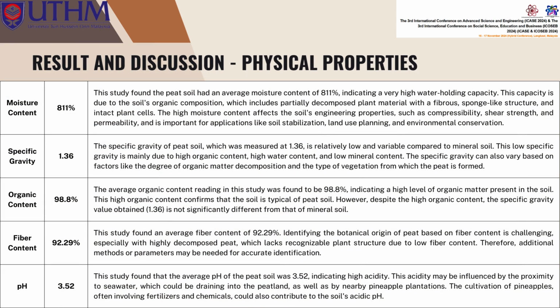For physical properties, this study found that peat soil has an average moisture content of 811%, reflecting its high water holding capacity. This is due to the soil's organic composition, including partially decomposed plant material and intact plant cells. The high moisture content influences the soil's engineering properties, such as compressibility, shear strength, and permeability, which are important for soil stabilization, land use planning, and environmental conservation. Peat soil has a relatively low and variable specific gravity of 1.36, primarily due to its high organic and water content and low mineral content.